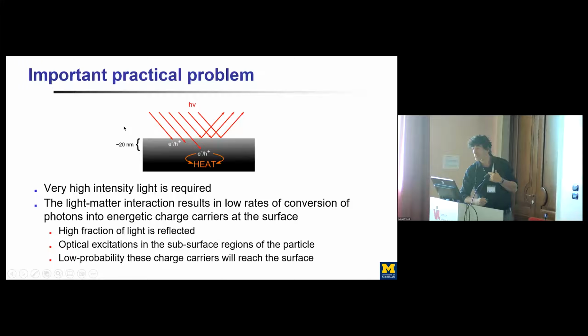fraction of your light, but also the light that goes into the metal creates these electron-hole pairs, and these electron-hole pairs are created far away from the surface. And before they can bubble to the surface and activate these chemical bonds on the surface, their energy is lost through collisions with other electrons and the phonon bonds. So you essentially end up heating the surface before you can selectively or efficiently move these electrons all the way to the surface to excite chemical transformations.